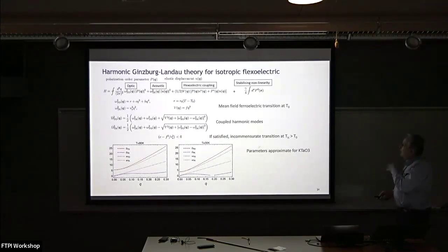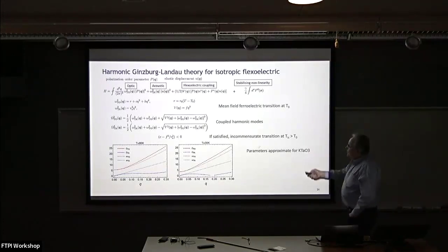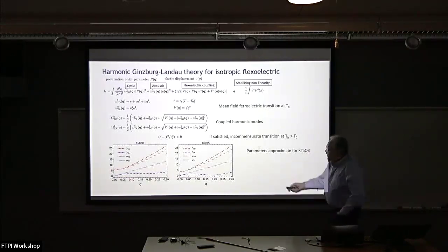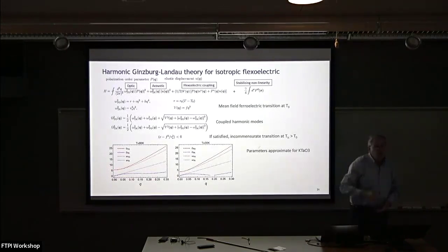This is just to show you how it solves the equations. I'm going to do the simplest self-consistent field theory that one can do, or if you like, applied Landau theory for the polarization. So some optic mode which is softening, with a stabilizing nonlinearity, coupling to acoustic fields. But to understand what might happen, I just put in some approximate parameters for something like actually potassium tantalate. If you have your theory without this coupling, you will have some, so this is omega versus Q. So this is the TO phonon, just coming down and getting very soft. And that's the TO phonon whose vanishing produces the divergence of the dielectric susceptibility.